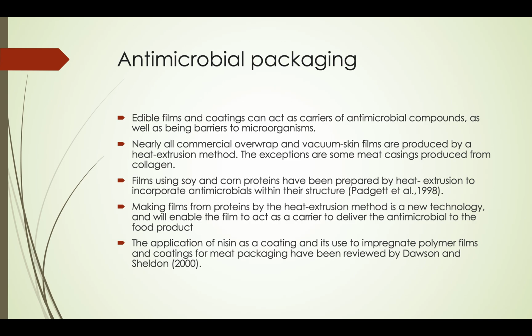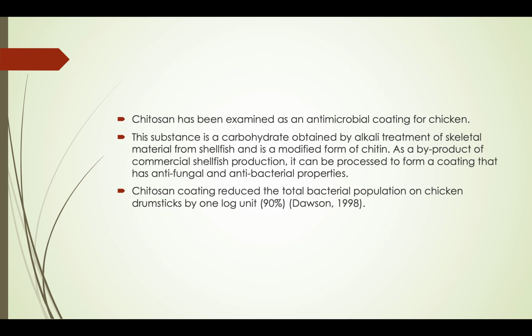The application of nisin as a coating and its use to impregnate the polymer film and coating for meat packaging have often been used. Chitosan has been examined as an antimicrobial coating for chicken products. This substance is a carbohydrate obtained by alkali treatment of skeletal material of shellfish and is a modified form of chitin. As a byproduct of commercial shellfish production, it can be processed to form a coating that has antifungal and antibacterial properties. Chitosan coating reduced the total bacterial population on the chicken drumstick by 1 log unit, which is about 90% of its total population.